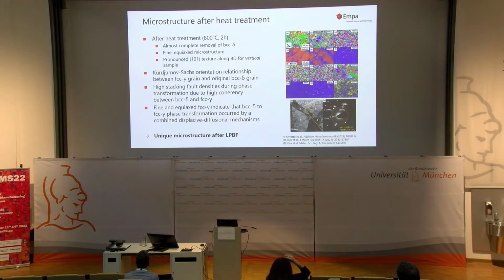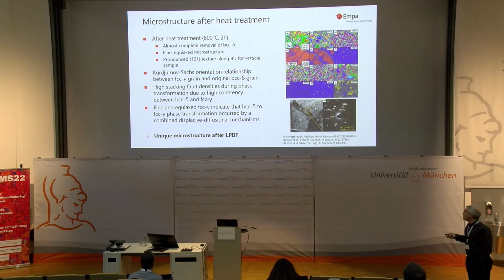So, of course, if we want to do something with it, it's good to get rid of this delta first. So we went into also an extensive heat treatment study, and there you can see it at different temperatures. We fixed the time to 2 hours, so you can see that the delta transforms into the gamma. So we have a nice temperature at 800 degrees Celsius, where we could fully convert the BCC into FCC.